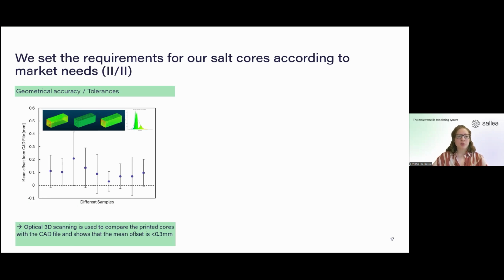But you can see overall that the mean offset from the CAD file is roughly lower than 0.3 millimeters. Of course, the standard deviation here is a bit bigger, but I would say on average it is below 0.3 millimeters. Now, what is still to be done here is that we further compare different such salt core samples with each other to know how reproducible our process really is. But from what we have seen so far, it is actually quite reproducible from the 3D printing aspects.